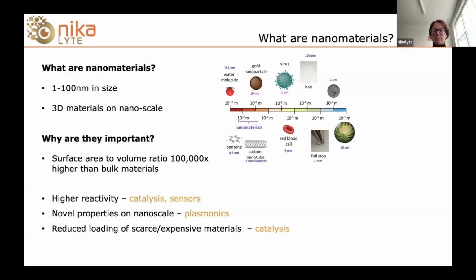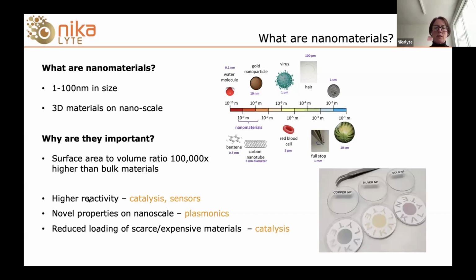We're not only seeing scales of improvement in reactivity, we're also seeing novel new properties appearing for materials that don't happen in the bulk. Here I've put a nice little picture of some samples that we've produced in our NL50, showing the plasmonic effects on very common materials such as copper, silver, and gold at the nanoscale. You can see the colors, which is a plasmonic effect due to the size of the nanoparticles, that they appear completely different at the nanoscale to what they appear at the bulk. And it's these properties that we can harness in our sensors, and I'll talk a bit about that later on.